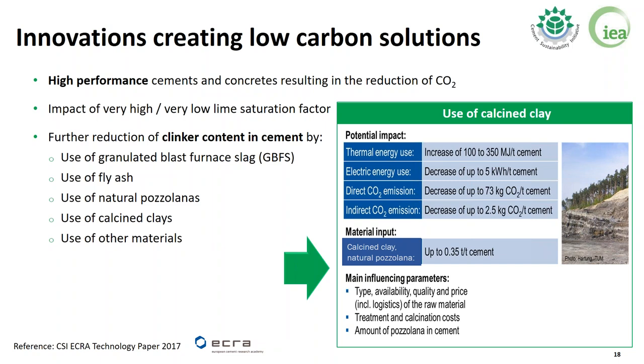Solutions for which technology papers are available are high performance cements, for example, ultra high performance concrete, and the intent here is to reduce the volume of concrete per square meter of application, very low lime saturation factors, and also a series of reductions of clinker content using alternative materials like, as we have seen before, granulated blast furnace slag, fly ash, natural pozzolana, other materials, for example, including silica fumes, industrial or agricultural ashes, and as said before, calcined clay.